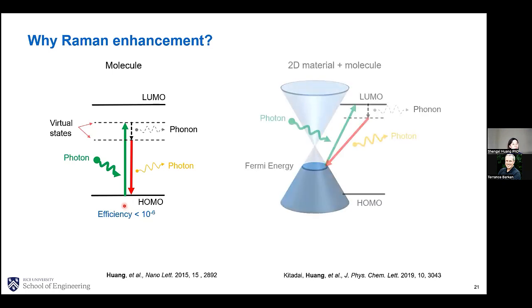So now if we actually have a layer of 2D material adjacent to these molecules, the 2D material will have continuous electronic states, and the Raman process from the molecule can actually utilize the real electronic states in the 2D materials. And in many cases, it can form a resonant Raman condition, and this will drastically enhance the Raman intensity for the molecules. As you can see, one example here.